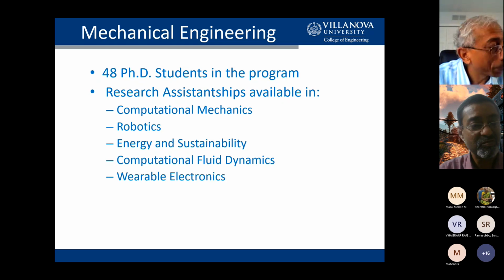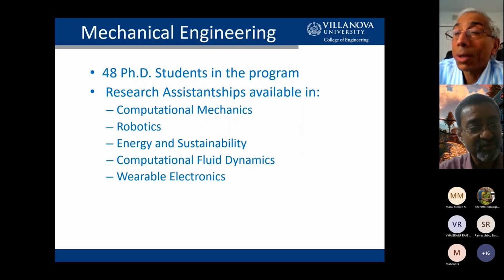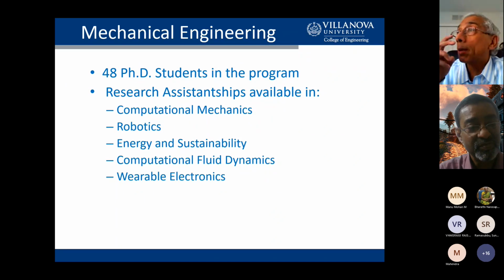I would say, instead of making predictions like that, I would just go back and do it, because the costs are not too much on the modeling side. So I would go back and redo the whole GA-based optimization for the composite material, and then find out what the edited spectrum is for that, because the failure modes are going to be different for a composite. The damage development modes are going to be different for a composite versus an aluminum metal, for example, and the crack growth da/dN curves are different. So rather than guessing, or even educated guessing, about whether I can use the one that I developed for a metal for a composite, I would just go ahead and do the modeling and figure it out.